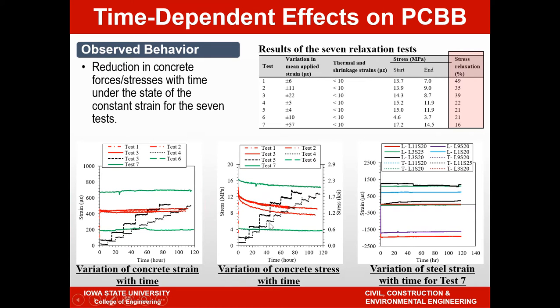The second figure shows the relaxation losses in the green and red curves. The black curves don't quite indicate this because the actual target line was much higher. The values that you see here are after losses, but one thing to observe is that between each step you can see the drop in stresses, which is because of the relaxation taking place in that member. On the right-hand side, you can see the strains in the last test, which is the beam, where the strain gauge data of the reinforcement shows that strains were kept constant during that test as well.